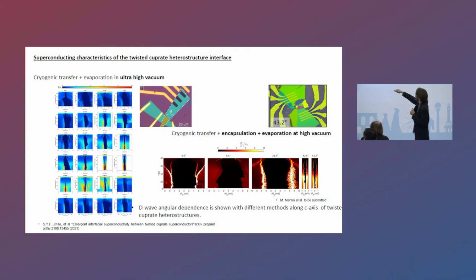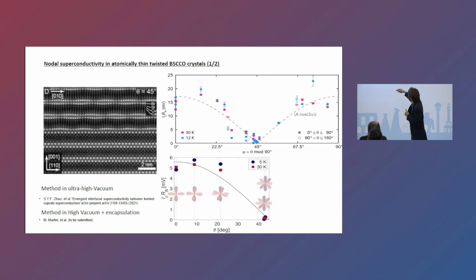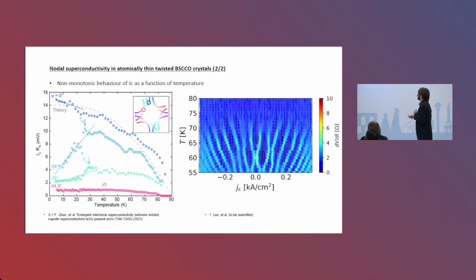If you look at the raw data, you can already see in the dynamic resistances that there is some change depending on the angle, where each plot is an angle. And now, if you look at the TEM picture, you see the quality of the interface that we have realized, of the supermodulation on top of the BISCO flake. These are atoms that you see, and where you see this modulation is basically where you have torn apart the crystal. And you see that the ICRN for the different methods that we have used always shows a d-wave dependence. I will very quickly finish.